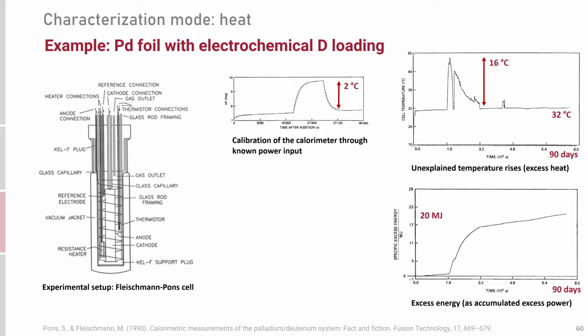with deuterium. Here's a calibration pulse that shows the performance of the calorimeter, and here is an excess heat burst that lasted many hours. Down here you see the integration of excess heat to arrive at a total energy released from that sample of about 20 megajoules.